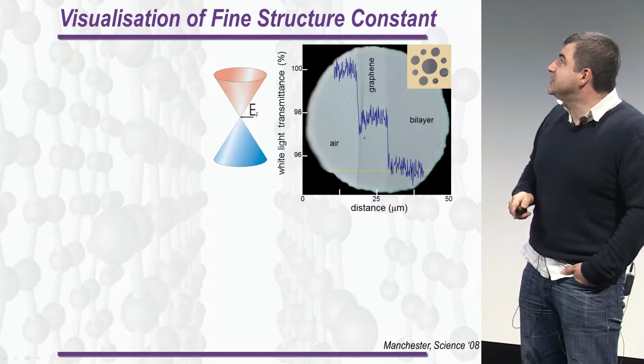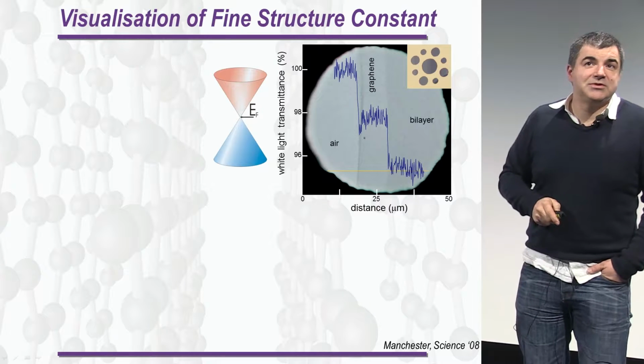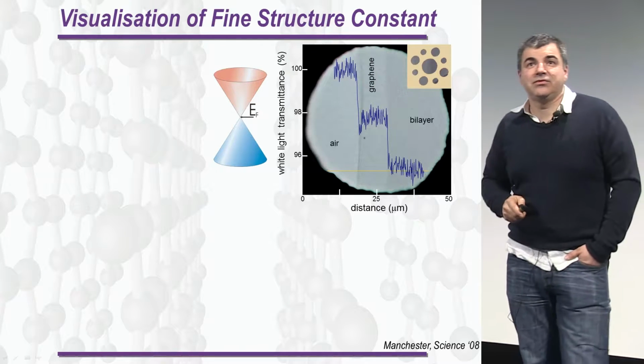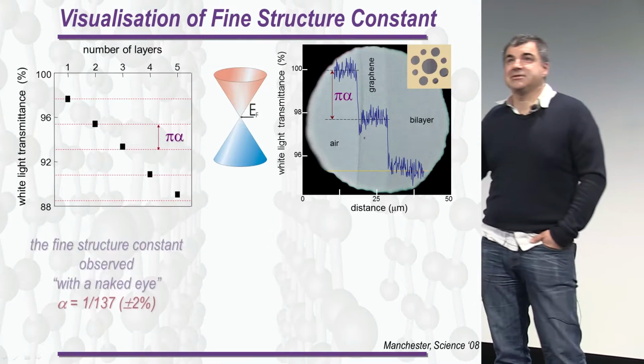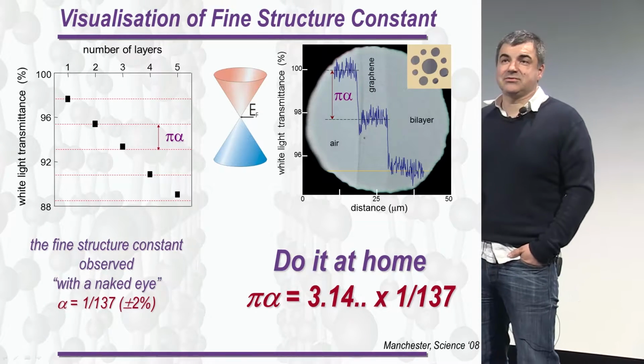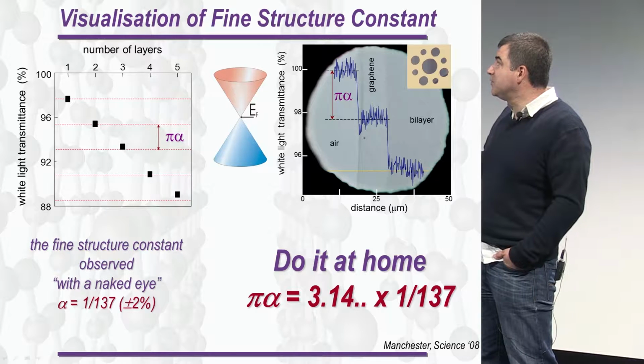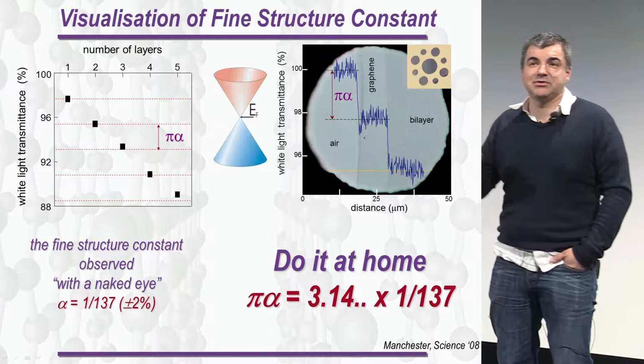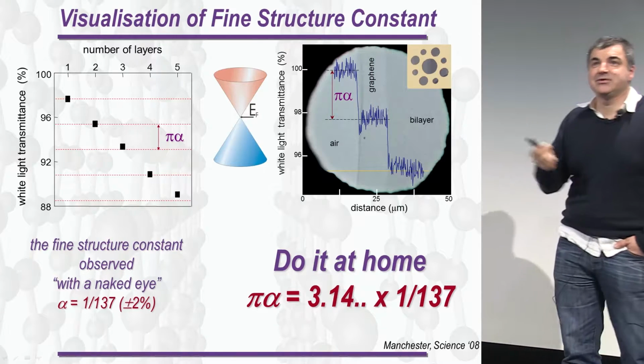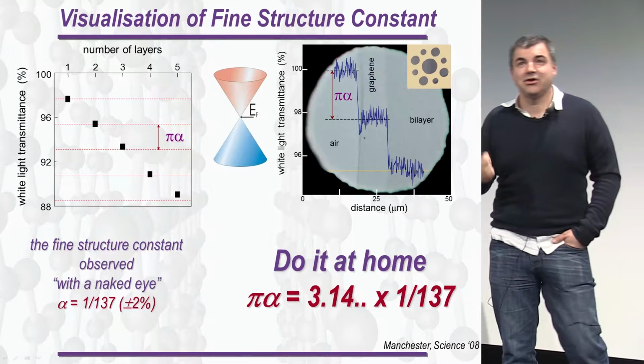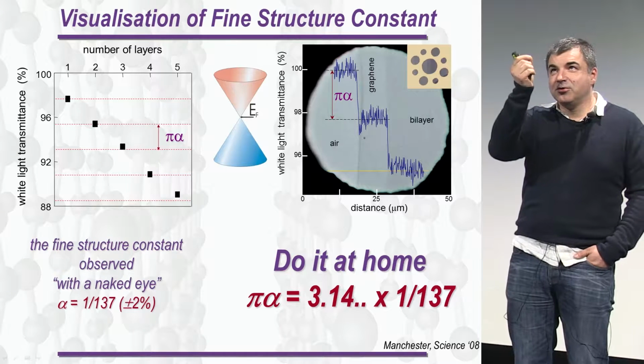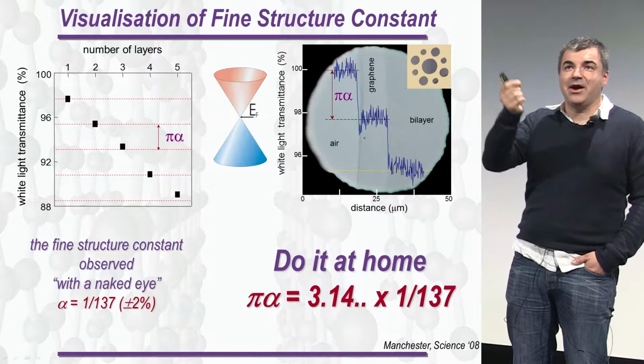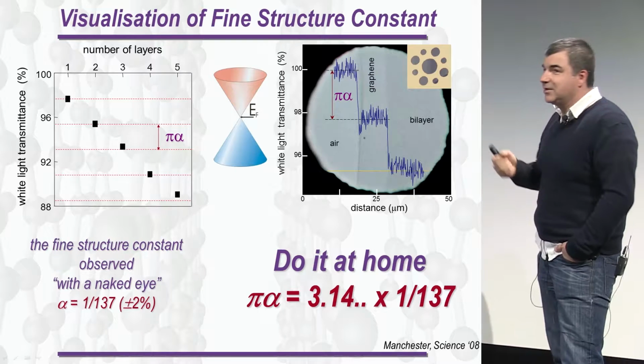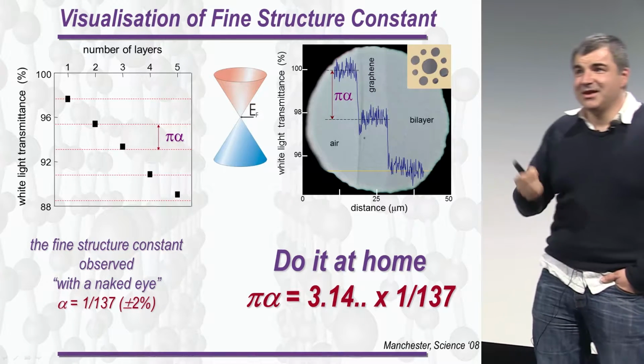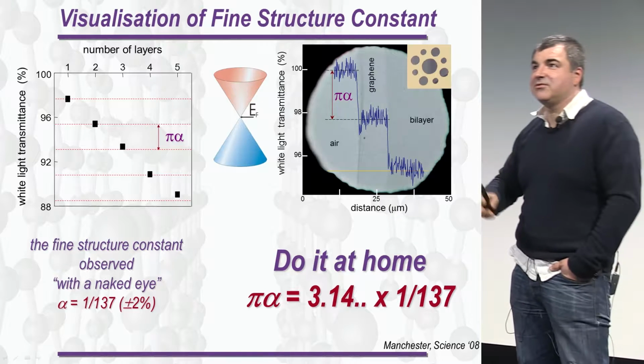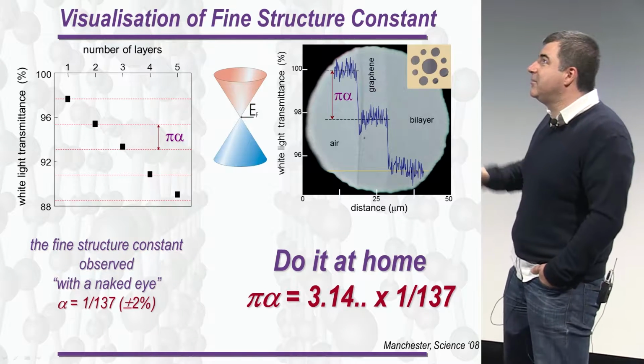The interesting part is that this number, 2.3%, is given only by the combination of the fundamental constants. It is pi times alpha. Alpha is the fine structure constant. Do it at home, 3.14, divide by 137, you get 2.3%. So if you ever forget the most fundamental constant of this universe, the fine structure constant, you take graphene, look through, measure the contrast, divide by pi. That's the most fundamental constant of this universe. It's quite easy to measure. 2.3% for a physicist, it's a huge number, very easy.